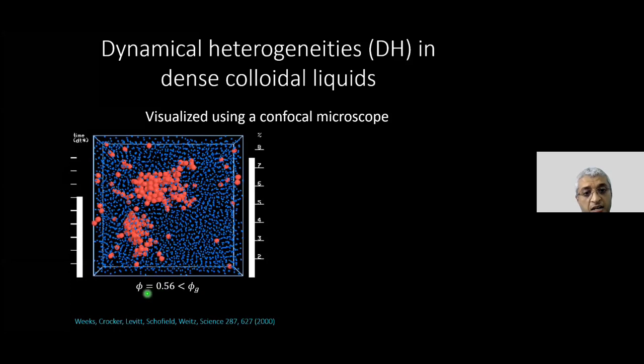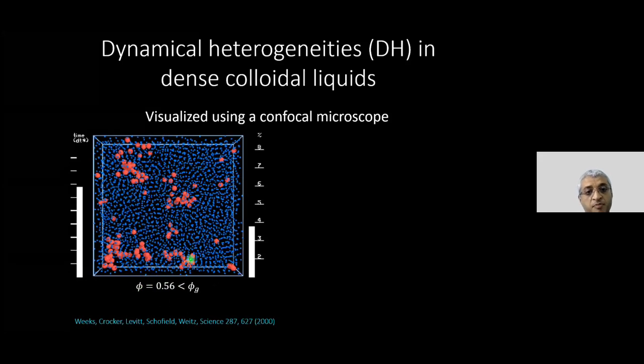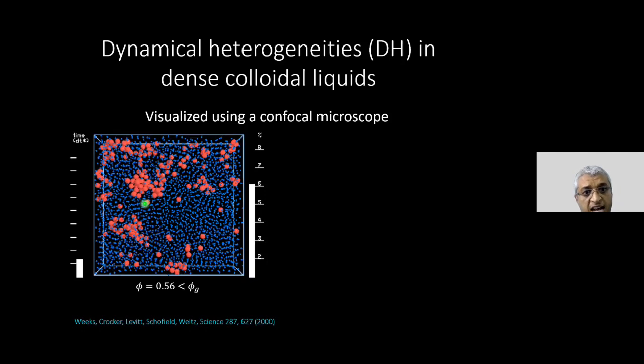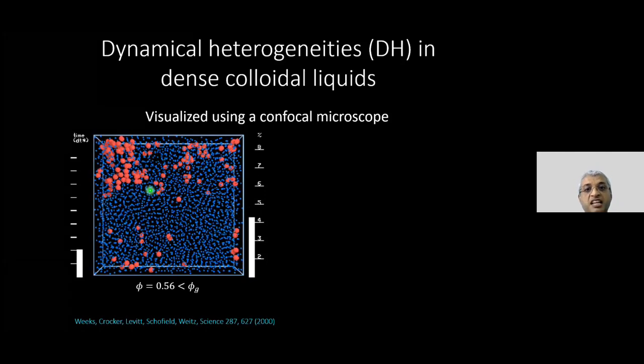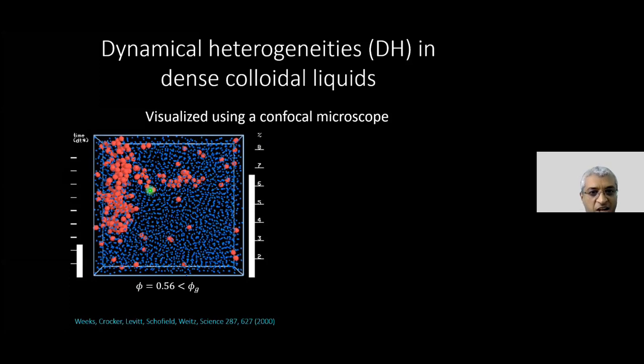And I'm doing this for a volume fraction of 0.56, which is below the glass transition volume fraction. And what you see in the dynamics is basically that particles that move quite a bit are spatially clustered, okay? And these are the dynamical heterogeneities that people had been talking about.